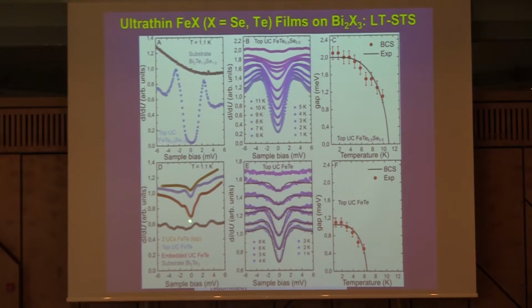On the other hand, if we look at the temperature dependence here and study this quantitatively, we can observe basically that this behavior follows nicely a BCS type behavior. We can do a very nice fit yielding a transition temperature around 6.5 K. We can do so for the related ternary compound, which is shown here.